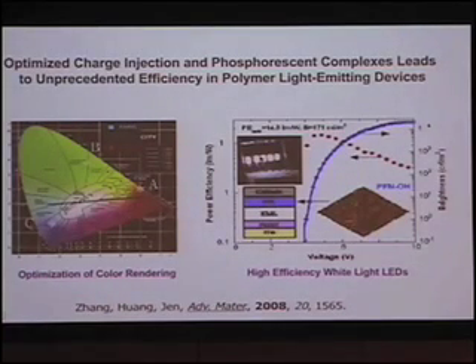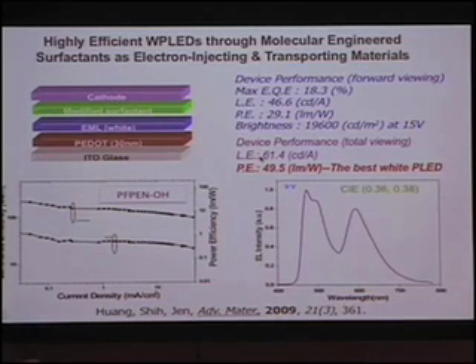So by utilizing both the hole transport layer and this conjugated surfactant, and by taking two relatively efficient complexes, a blue emitting complex and an orange emitting complex, you can adjust the ratio and hit the sweet spot. You can have very nice white light emission. In 2007 this already exceeded the incandescent light bulb. Recently, by further doping in a little salt to improve the mobility of this conjugated surfactant, we have reached a power efficiency of about 50 lumens per watt. This is one of the highest ever reported for a polymer-based